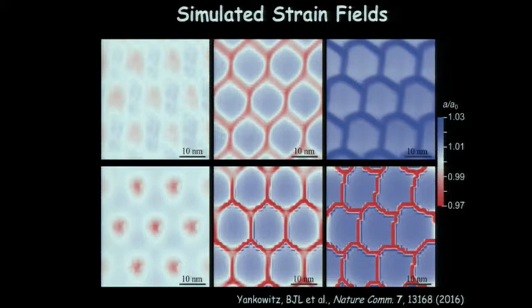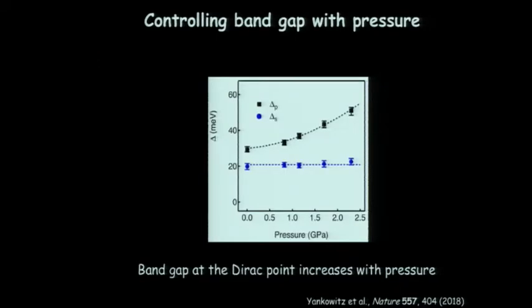And so there was some subsequent work on this by Cory Dean's group using a pressure cell. They put the graphene on boron nitride in a pressure cell and just increased the hydrostatic pressure, which is essentially the same thing as pushing the graphene down with the tip. And so what they saw there, this is the function of pressure. This is the gap that was measured at the Dirac point in black. And so they see that the gap increases at the Dirac point as a function of pressure.